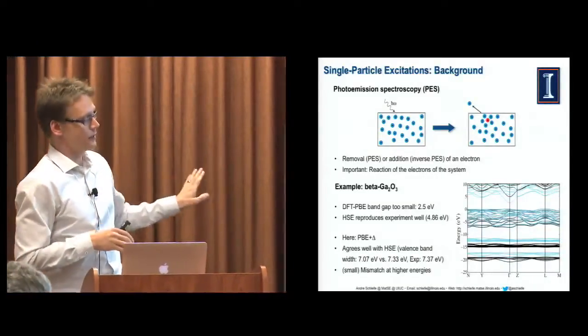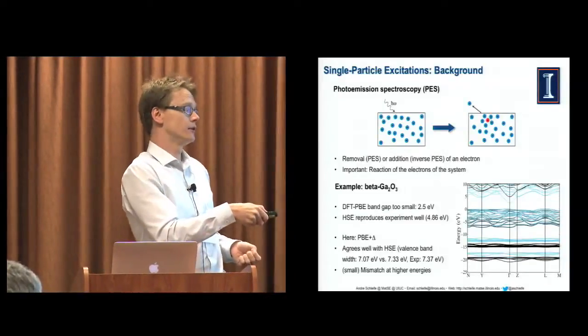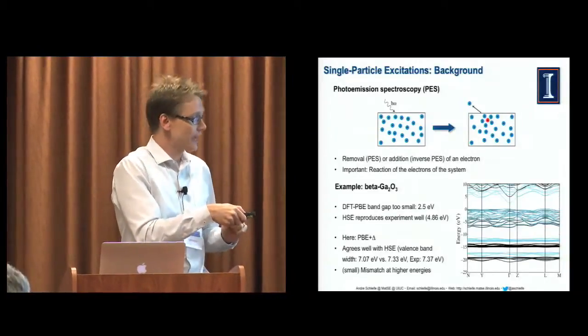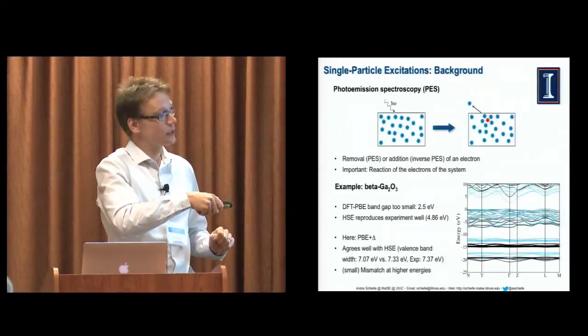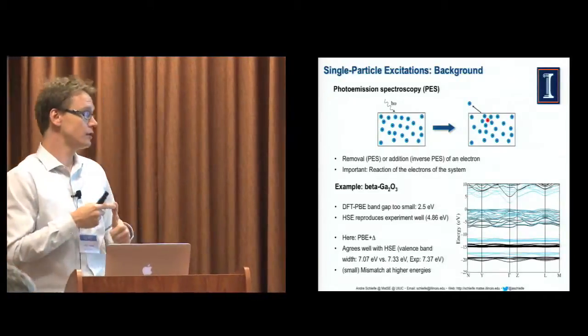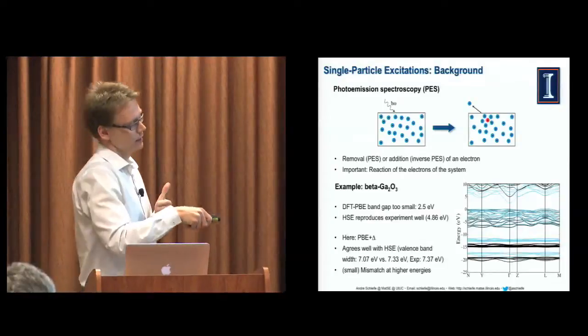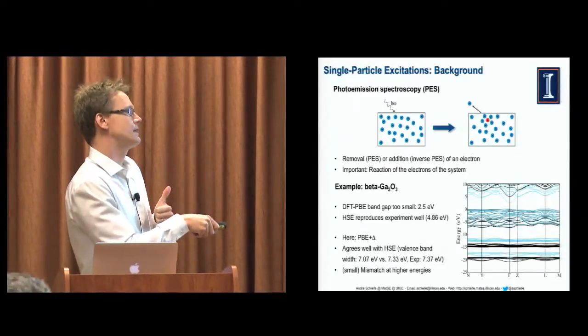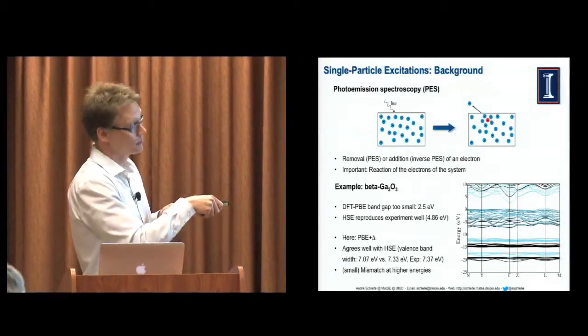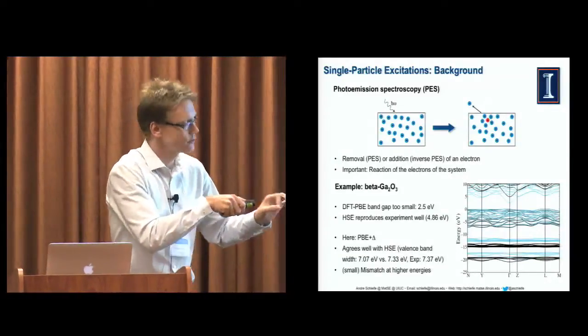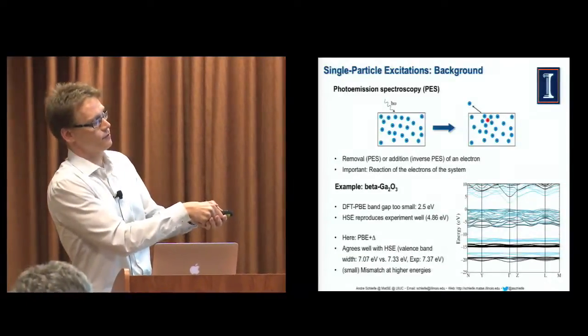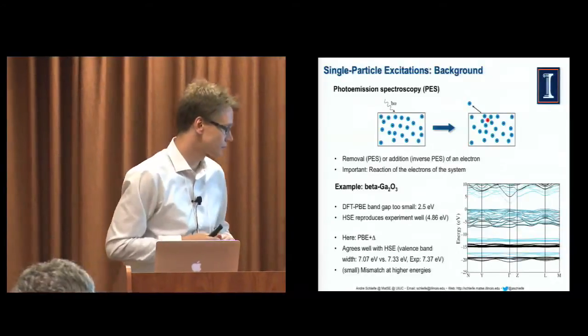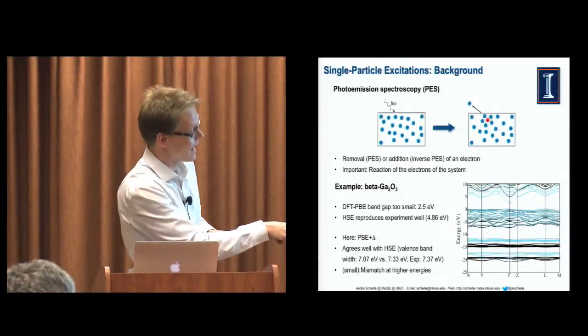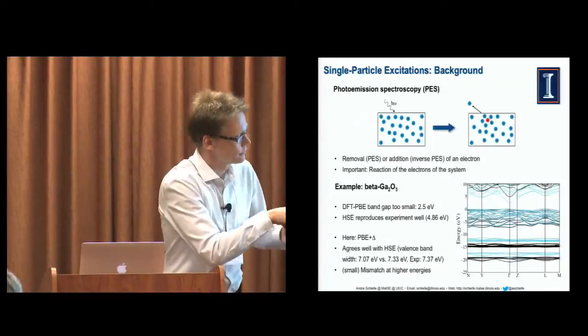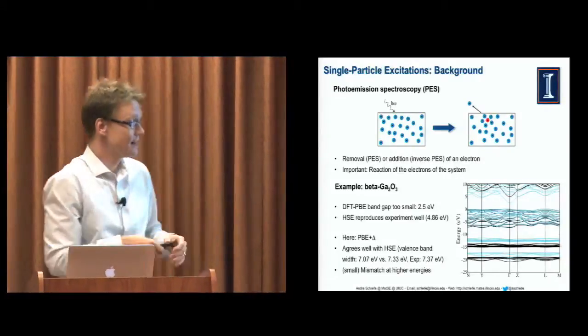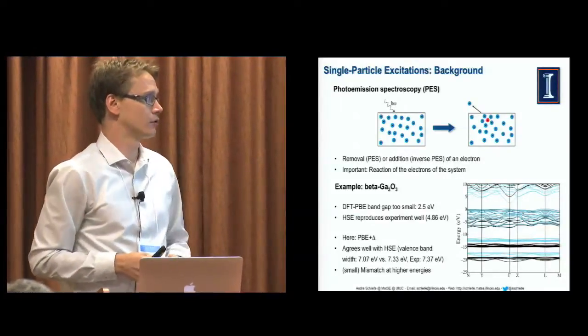Again, that was work that we did in the past, but we will use it as input to get optical properties. The take-home message is that this hybrid functional gives us a good band gap in comparison to experiment, so that's good. And then we approximate that by the so-called PBE plus delta method, where we use this computationally cheap approach and correct for the deficiency by opening up the band gap to the value that we got with the more complicated approach. And as you can also see, the mismatch at higher energies will not be just a constant shift. So you can see that those bands start to deviate. These are things that we have to tackle in the future.